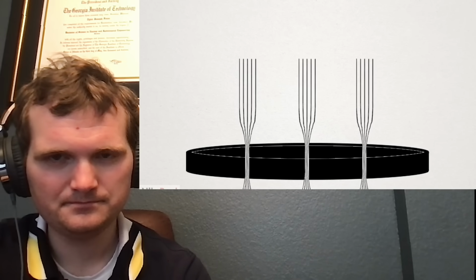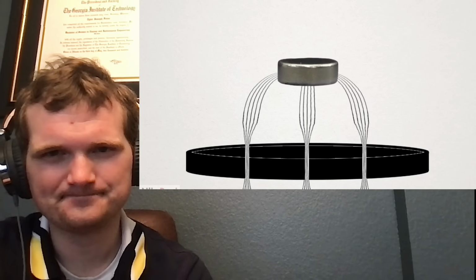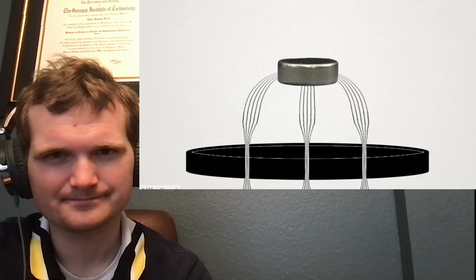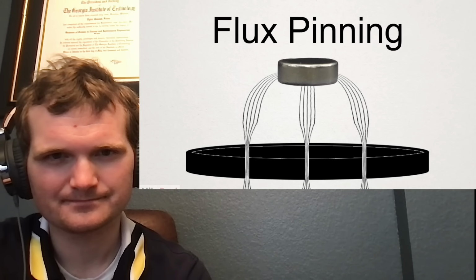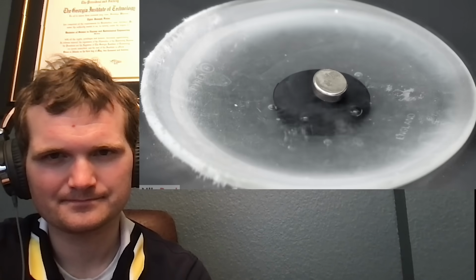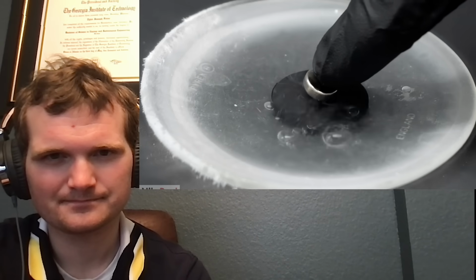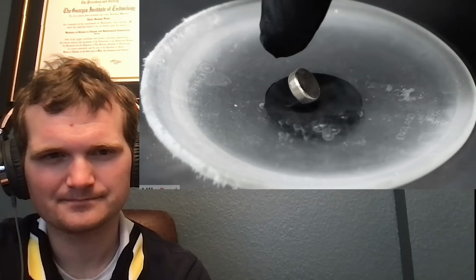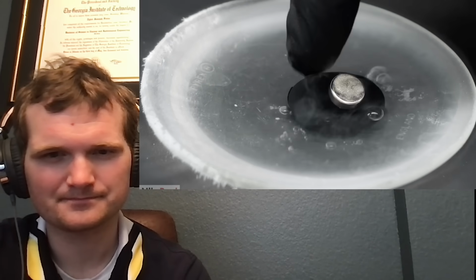But it doesn't, because there's actually another unique effect that's going on at the same time. The crystal structure of the YBCO isn't perfect, and small defects allow a bit of magnetic field to still get through. This causes small magnetic flux tubes to form, and they kind of act like tethers, and they hold the magnet in place. This is called flux pinning, and unlike the diamagnetism, the force is actually attractive. So even though the magnet's just floating there, it's still kind of connected to the YBCO, and if I push it around, the pellet moves with it.